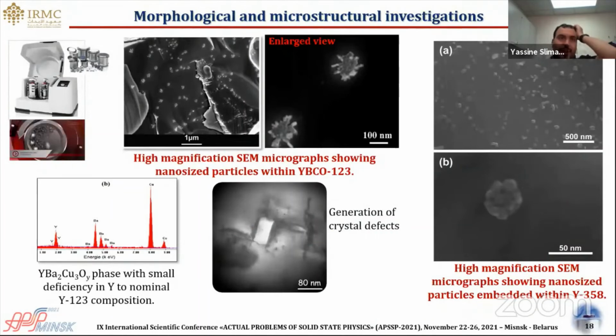This is also another example from our previous study where we studied the impact of high energy ball milling technique on superconducting properties. We found, for example, that the density of self-generated nano entities would have a great impact on the superconducting performances.